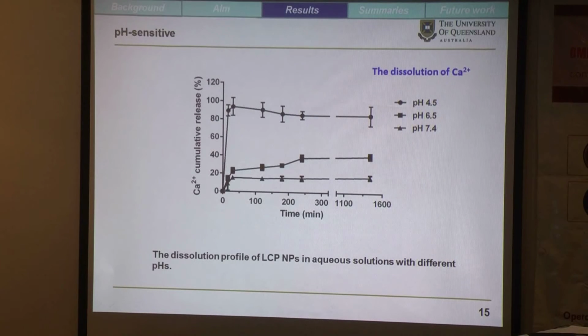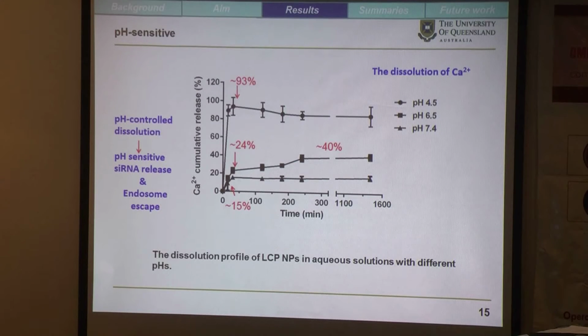concentration range. In order to examine the pH-sensitive RNA release property of the LCP nanoparticles, the dissolution of calcium ions from the as-prepared LCP nanoparticle was tested at various pH values. As shown in the picture, LCP nanoparticle exhibits a certain degree of dissolution at different pH values, and the accumulated dissolution of LCP slowly increased to 40% at the pH value of 6.5, while LCP nanoparticles stay pretty stable at the pH of 7.4. This result suggests that LCP nanoparticles have a favorable property of pH-controlled dissolution, which may induce pH-sensitive release and endosome escape.